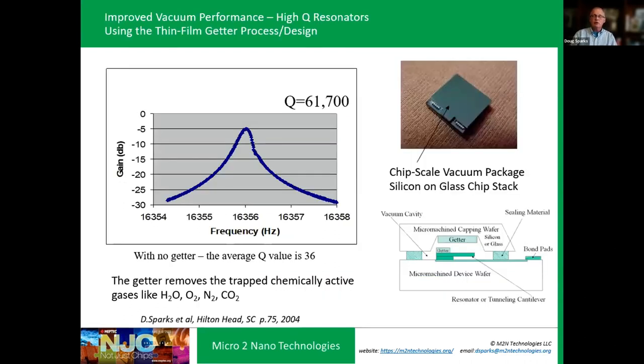One way to improve your vacuum packaging is through a thin film getter. Roger mentioned NanoGetter is the company I founded. That's where you use a thin film active reactive metal inside the cavity. It can be inside the top cap of the wafer. We even put some thin film getters on the non-moving inactive MEMS device area. And these reactive getter metals are kind of like a sponge. They will chemically trap oxygen, hydrogen, O2, nitrogen, and carbon oxide compounds.